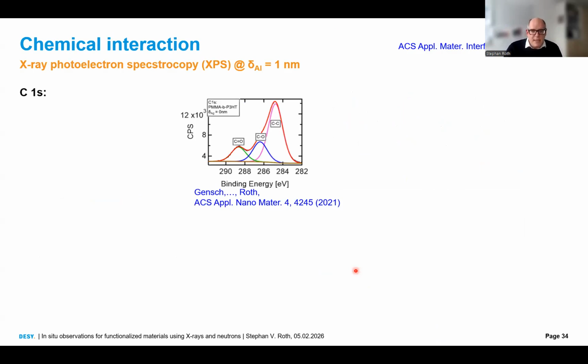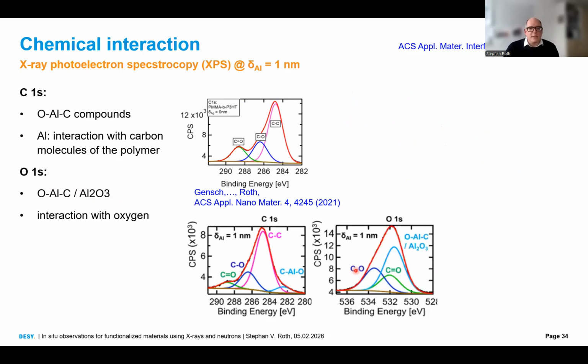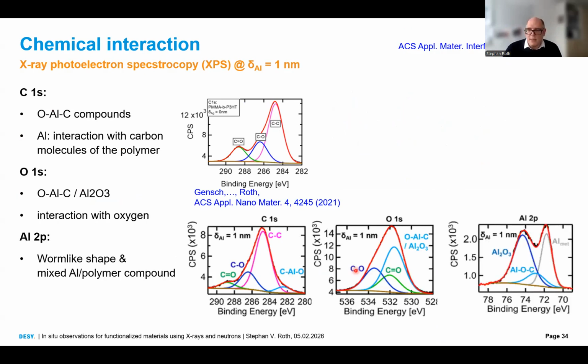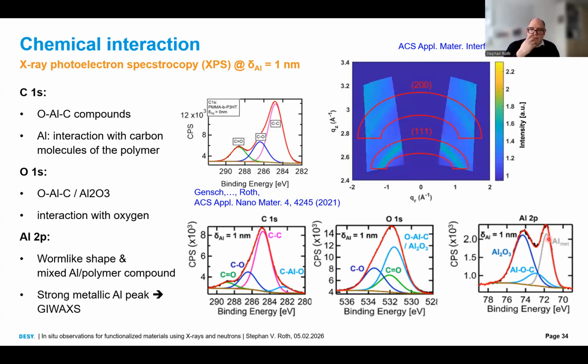Then with XPS, you can look at the chemical interaction. You will see in all spectra that actually aluminum interacts with the carbon molecules of the polymer. Aluminum interacts with the oxygen, nothing new. And when you look into the aluminum signal, you see a strong metallic aluminum peak, meaning that we have really pure aluminum growing. And this is then what you see also in the GIWAXS signal. Good. We have a nanostructure template. We start to see how the aluminum interacts with the different parts of the diblock copolymer, and we can create a full